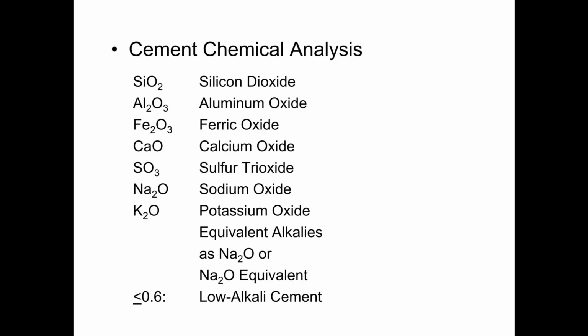But due to the potential for reactivity with aggregates, it's the sodium and potassium that we're generally going to pay the most attention to. Since there are different molecular weights between the potassium oxide and the sodium oxide, generally the potassium oxide is going to be normalized to a sodium oxide weight so that the total equivalent oxides can be stated as a function of sodium oxide equivalent. To be classified as a low alkali cement, that sodium oxide equivalent has to be less than or equal to 0.6%.